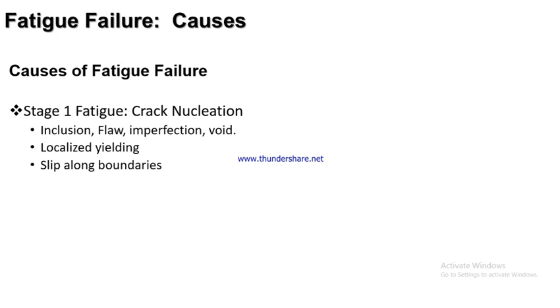The first one is what we call crack nucleation or crack initiation, which can easily be caused by inclusions, flaws, imperfections or voids in materials. There is no particular material that is free of voids or that is a perfect ideal material. All materials have flaws or imperfections in them. So all these can easily cause fatigue, even while we try to control them during the production or processing history of the material. During mechanical assembly too, we can sometimes incorporate them into the materials or into the mechanical system.